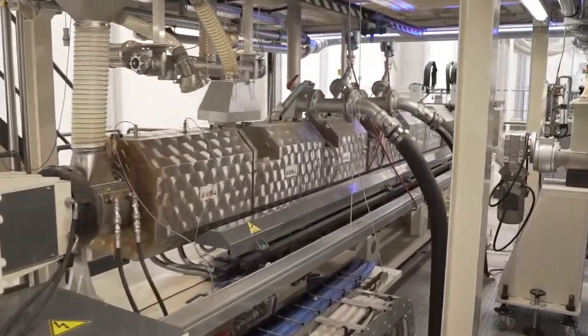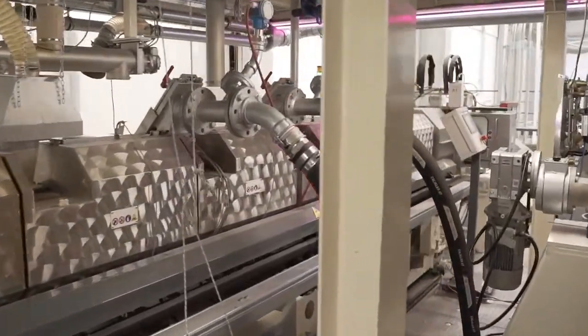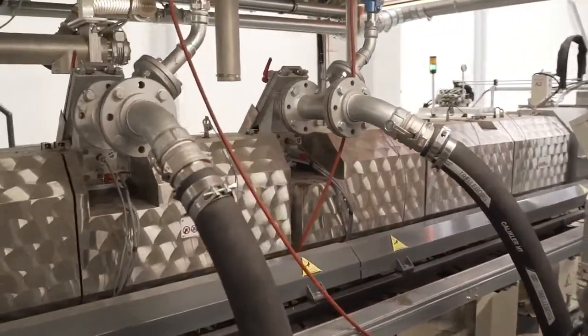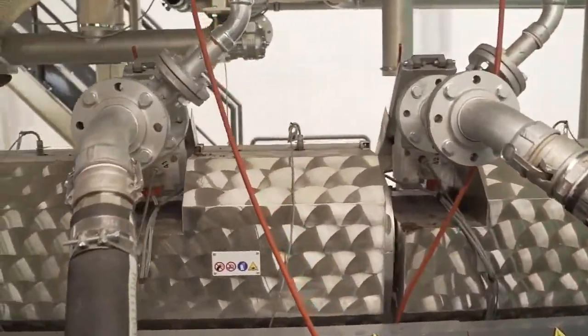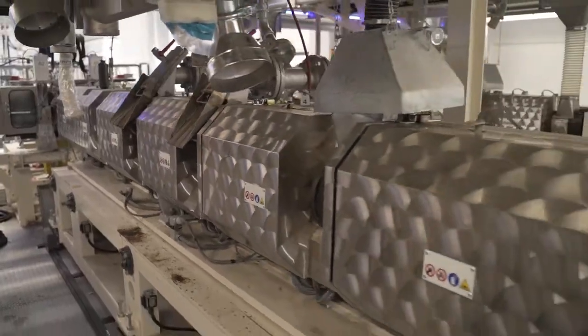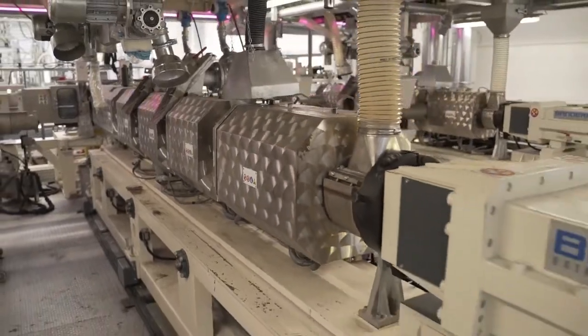When required, the twin screws can process polymers with mineral fillers in pellets or in powder through side feeders, or to provide physical foaming by gas injection on the extruder barrel. One of the major benefits offered by the Bandera twin screw is the degassing efficacy in processing PET, PLA and polystyrene with no pre-drying. Obviously, this will reduce production energy cost. Similarly, such an efficient degassing improves also polypropylene quality.